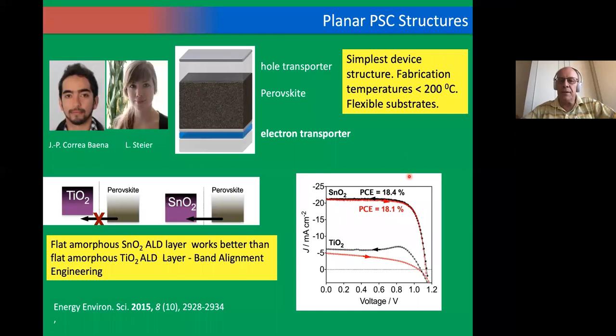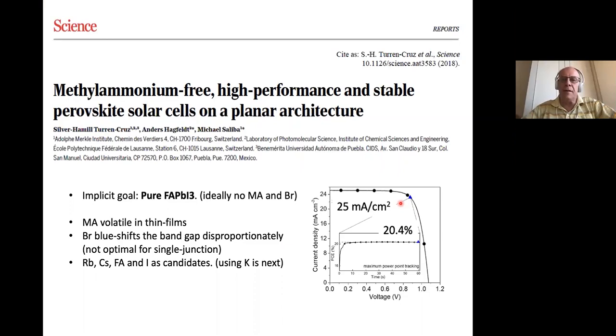Here was a kind of a breakthrough paper on planar devices from Juan Pablo and Ludmila, measuring 18% efficiency. So we have continued with that, and one of our more recent works with Silver here and Michael Saliba. And this is a direction which is now happening, and that is to try to go as close as possible to pure FA lead I3.